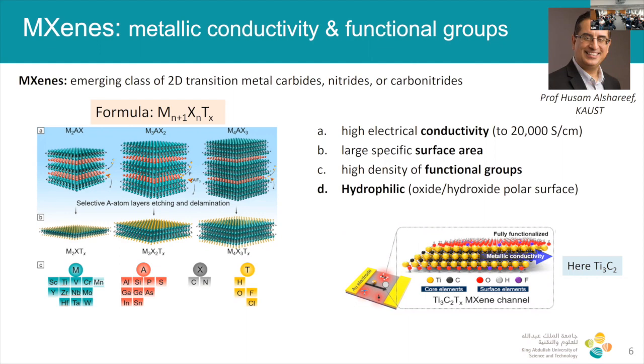Of course, hydrophilic, which is wonderful. That means I can be putting some aqueous media around that and aqueous solutions and working with something that we're typically used to working with. And they also remain very, very stable in solution over time, in water over time. So this is what you want to imagine when you're looking at this 2D nanomaterial. On the surface, everything red is these nice hydroxyl groups. And in the middle there, you have this carbide network where electrons can be transported very, very quickly, very easily.